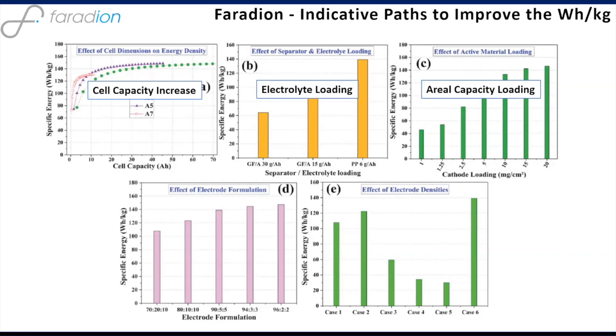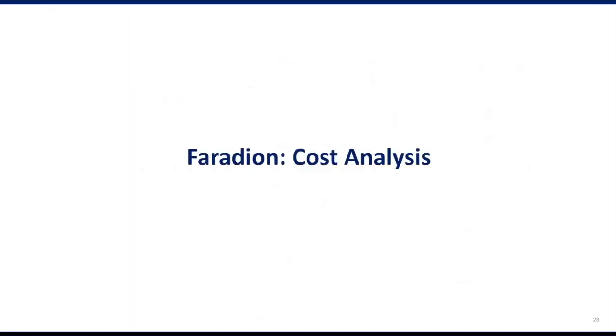Another simple way is increasing the thickness of the electrodes. As I said earlier, this is getting to high areal capacity electrodes, generally measured in milliamp hours per square centimeter. So we're moving that ahead at all times. If you can get to high areal capacity, then you get better packing efficiency and you need fewer layers in the cell. Electrode formulation is about getting to higher loadings of the active materials in the electrodes, and we're doing that right now. As we're showing in this chart, our cathode active is running at 96%. So we've pushed that ahead, and we're still pushing that ahead in both cathode and anode. And lastly, you have to optimize the electrode density. This is generally in grams per cubic centimeter, and that comes down to how you control the porosity by pressure calendaring the electrodes. You have to get that right also to boost the specific energy.